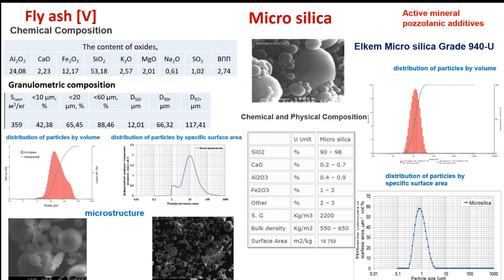Fly ash is an important pozzolanic material which, when mixed with cement, significantly affects the strength development of the cementitious composites. Fly ash increases durability and strength of concrete at later age, but at the same time reduces the early strength of concrete. It also reduces the amount of the water reducing admixture required to obtain the same consistency. Silica fume significantly increases the strength and durability of concrete, but it has a high water demand, so it requires the use of an increased amount of water reducing admixture.